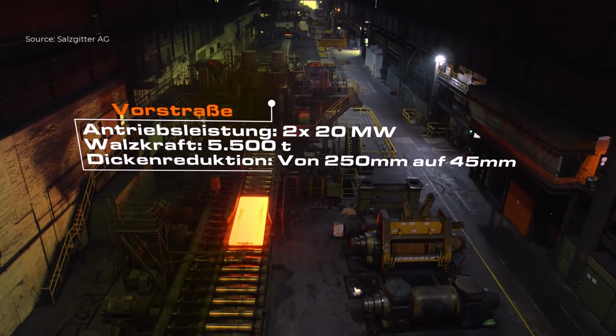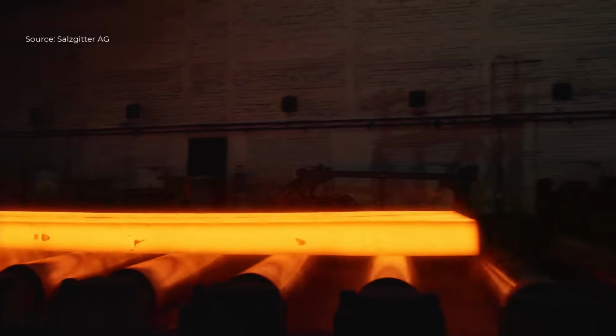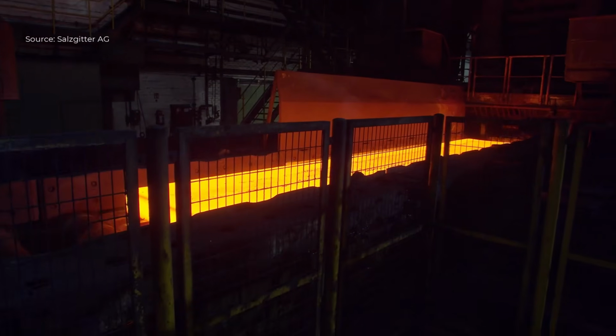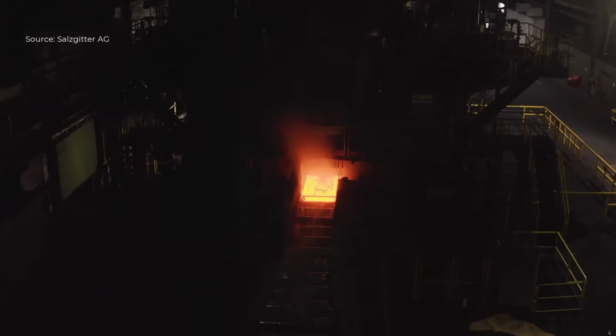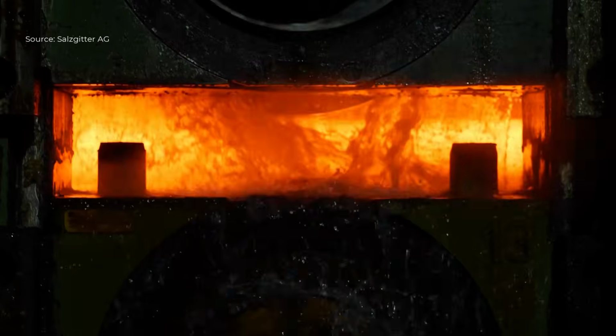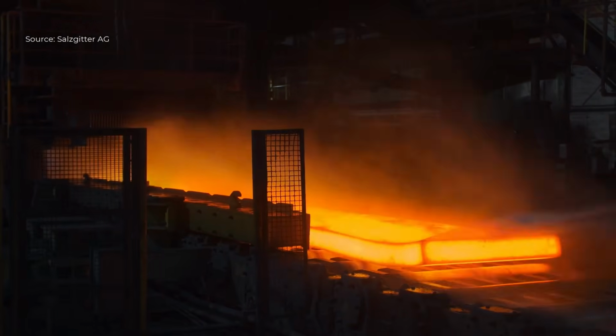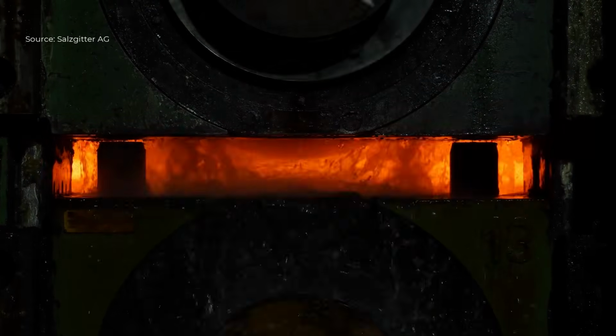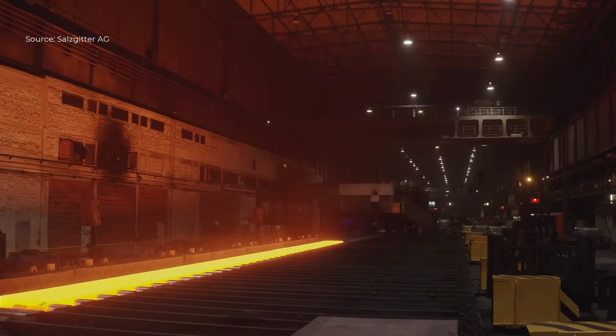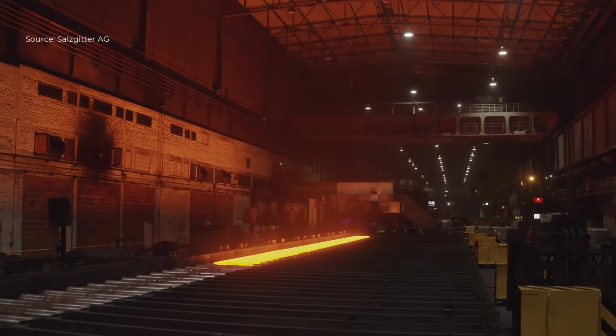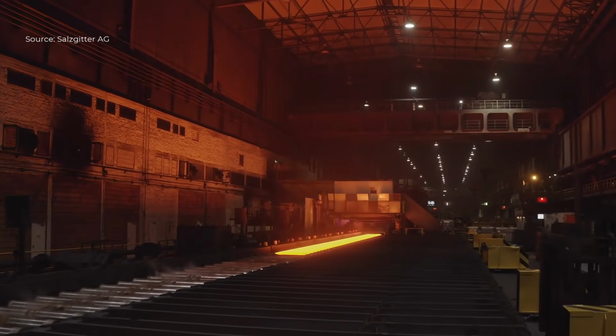The slab then enters the roughing mill, Vorstrasse. Driven by 2 motors with a combined power of 2 times 20 megawatts, the mill applies rolling forces of up to 5,500 tons. In several passes, the slab thickness is reduced dramatically from about 250 millimeters to 45 millimeters, while its length increases significantly.